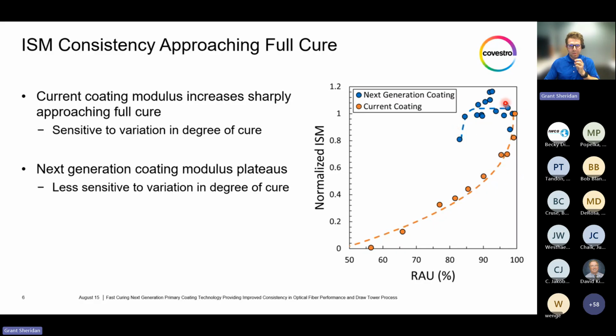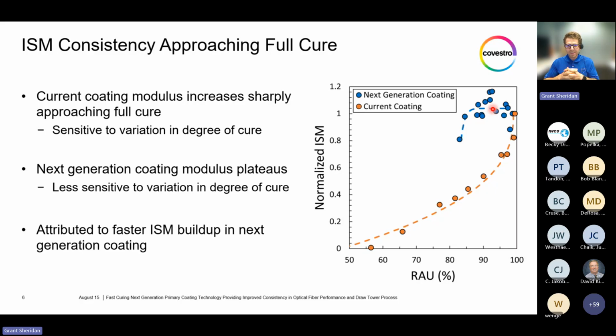Now, if we look at the next generation coating in blue, we can see that, unlike the current coating, the next generation coating plateaus with increasing RAU, leading to it being less sensitive to variation in degree of cure. We believe this significantly improves draw tower consistency, as any small variations in processing or in cure will lead to significantly smaller variations in the in situ modulus seen here. Additionally, we would anticipate that with subsequent curing steps, we would see a smaller jump in the in situ modulus as well. We attribute this improved draw tower consistency and plateauing to its significantly faster in situ modulus buildup in this next generation coating. We build up the polymer network, the mechanical structure, early on in the curing, and additional curing doesn't contribute as much, leading to the plateau.